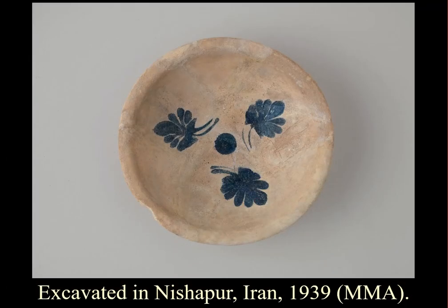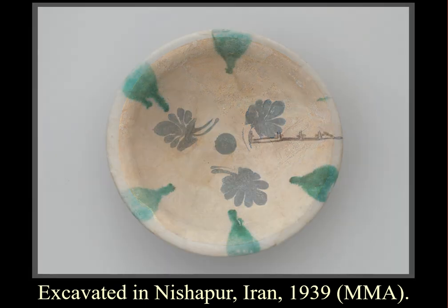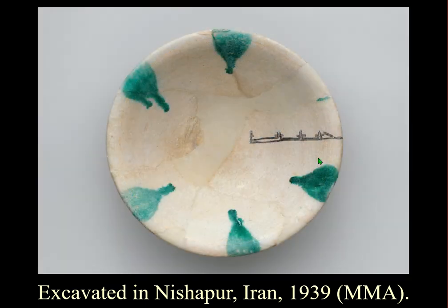From these excavations we actually have pottery from Basra in Iraq — the blue painted wares. The tin-opacified glaze with cobalt blue was only made at Basra, not made anywhere else in the world at the time. But they did copy them. This is a white slip over a pinkish earthenware body, with a black slip paint — probably with chromium in it — splashed with green, as some of the imports from Iraq would look like.